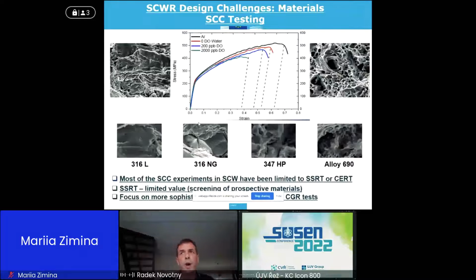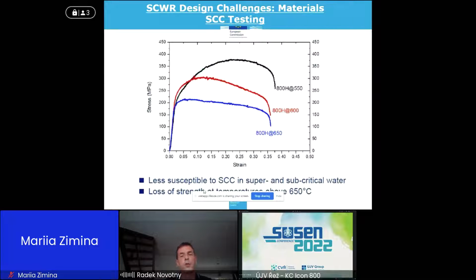And that's why we need to go to more sophisticated crack growth rate, fracture mechanics based tests, or SCC initiation tests. One example of the usefulness of the SSRT test is alloy 800H tested for SCC susceptibility at different temperatures, and we can see the degradation of yield strength and mechanical properties due to temperature. The alloy showed low susceptibility to SCC in super and subcritical water.